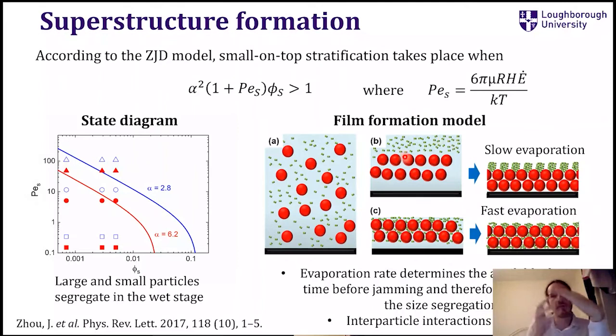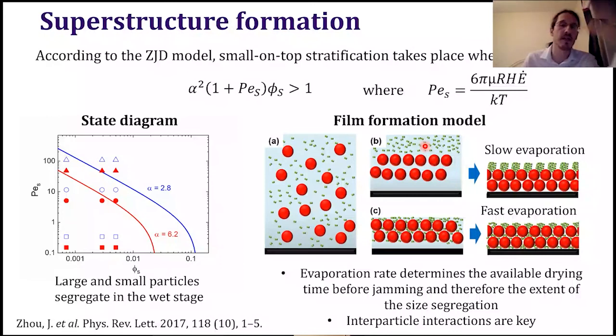So the particles start to segregate, but when you're evaporating really slowly, you have more time for these particles to segregate, and you have more small particles on top of the large ones in the dispersion. Whereas when you're evaporating faster, these particles get trapped, the small ones in between the large ones. So when it evaporates completely, for slow evaporation, you have quite a lot of small particles that are pushed on top of the large ones, and then they form these taller structures. But if you're evaporating faster, then you have less zinc oxide available at the top to form these structures, and that's why they are not as tall as the other ones.